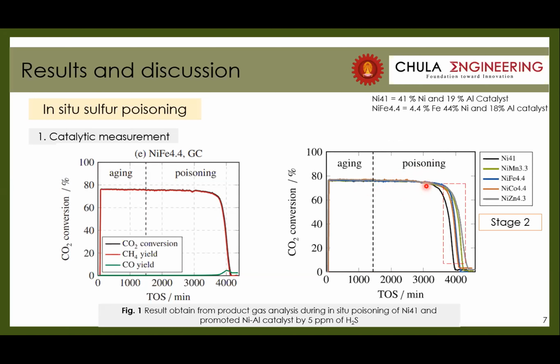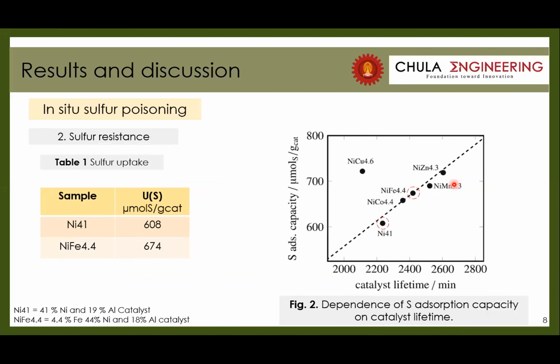In stage 2, the poisoning zone moves to the rear end of the fixed bed, and the non-poisoned fixed bed is small, resulting in carbon dioxide conversion dropping very fast. And the last state is when the fixed bed is saturated by sulfur, and the catalyst's methanation ability is completely lost.